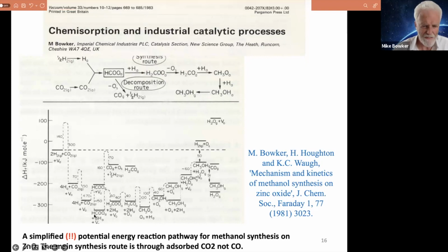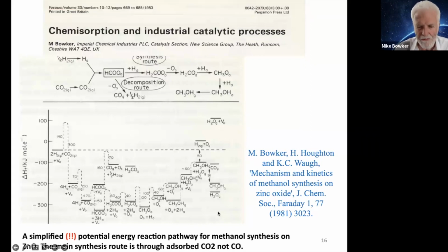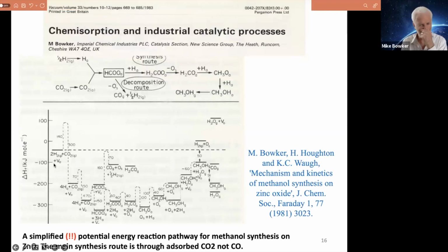You can see here that the formate is the bottom of that potential well and is most likely to be rate determining in the methanol synthesis. That formate, you can see the important role here of the vacancy. That's a crucial thing that's not in most potential energy diagrams of methanol synthesis.